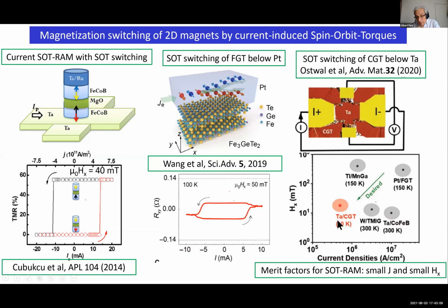And you can see the best results are obtained for a 2D magnet, CGT, with a relatively small field Hx and a very small current density. Of course, these materials seem to be interesting for applications, provided that the ordering temperature can be enhanced above room temperature, which is not the case so far. But in the future, if these materials can have a Curie temperature well above room temperature, it will be possible.